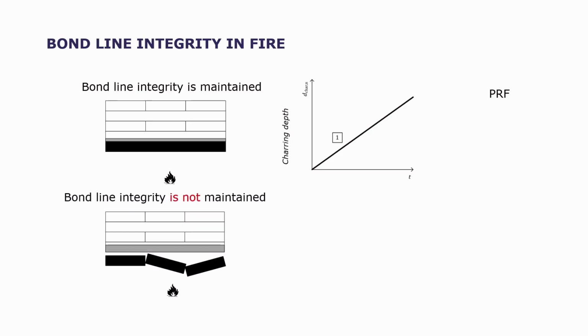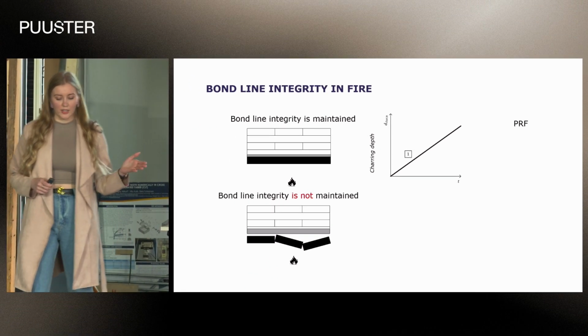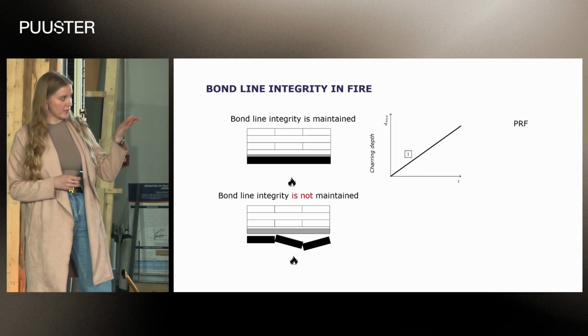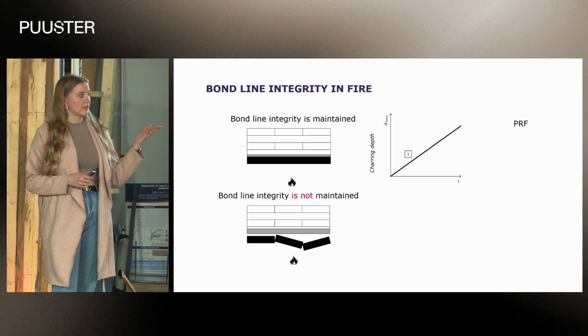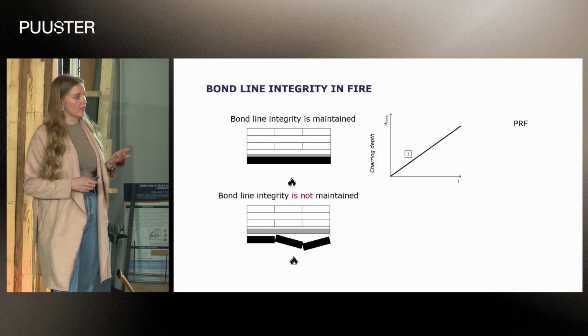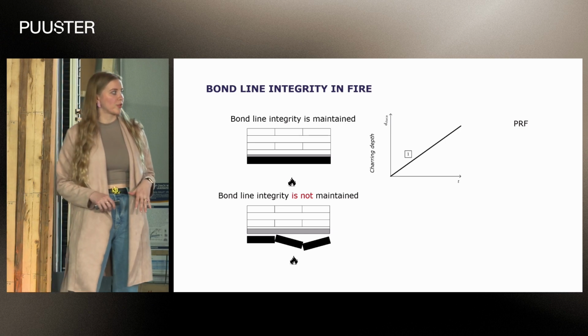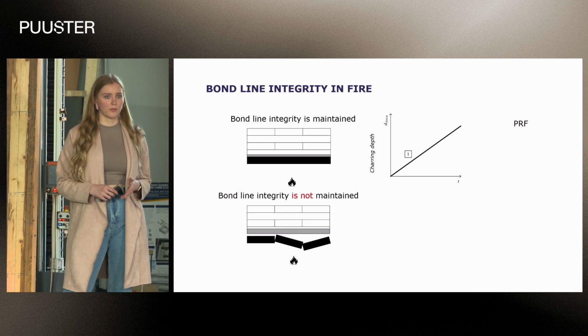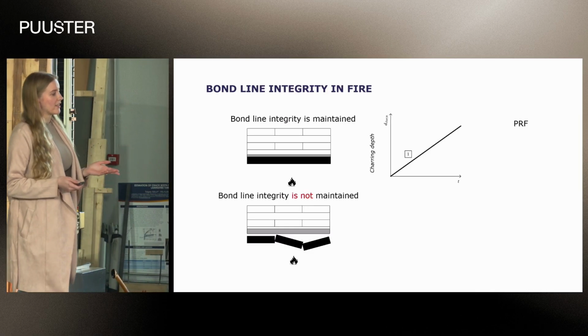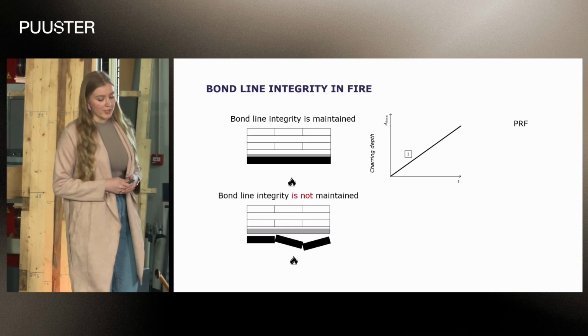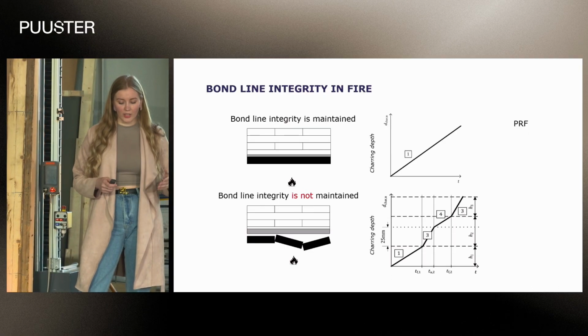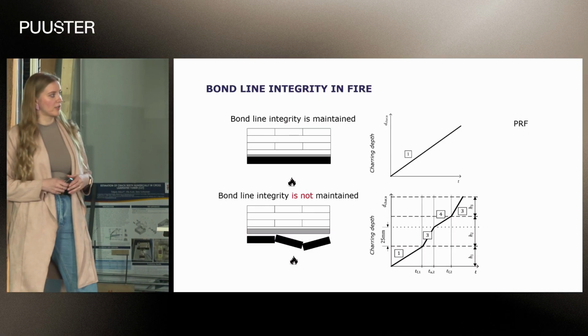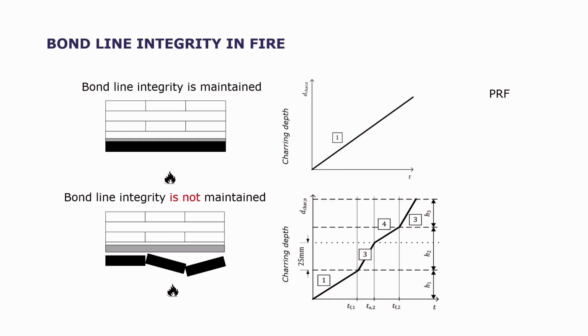But what was discovered during testing was that for some of these adhesives, the bond line integrity is not maintained. So that means that when the char layer forms and it reaches the adhesive bond line, the adhesive softens, loses its strength, and the char layer falls off, which means that the timber behind the char layer is completely exposed to fire now. So it starts burning faster, or charring faster. And this is taken into account in the new Eurocode with a second charring model, the step model.